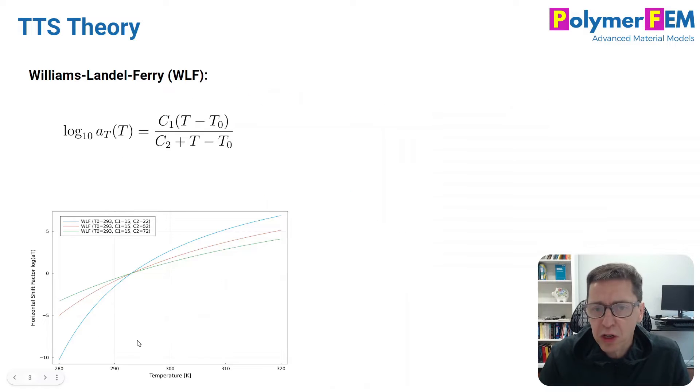Let's talk first about the WLF equation, Williams-Landel-Ferry. It's a very common equation often discussed in terms of applying it to amorphous polymers above Tg or close to Tg. Here's the equation for it. It looks like an interesting equation with three parameters: C1, C2, and T0.